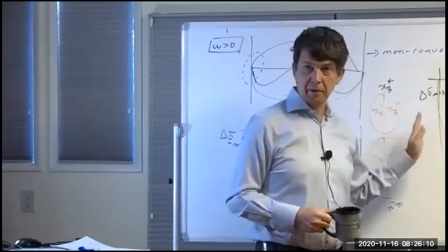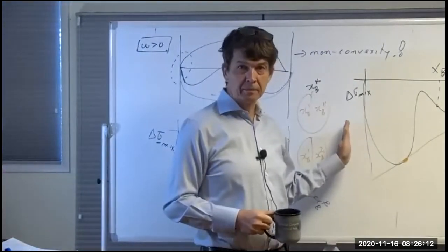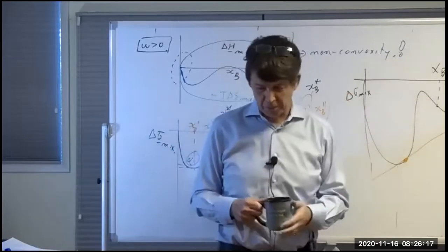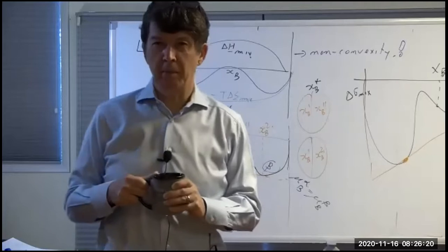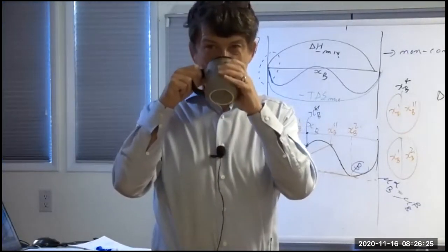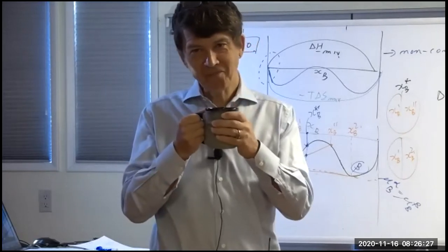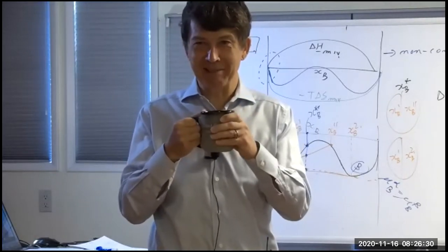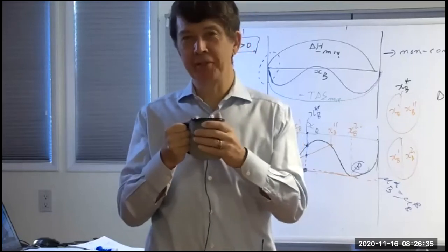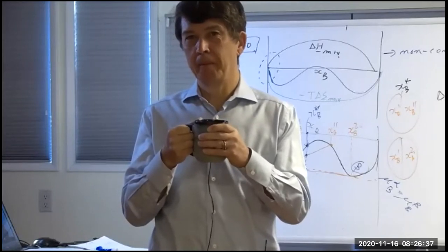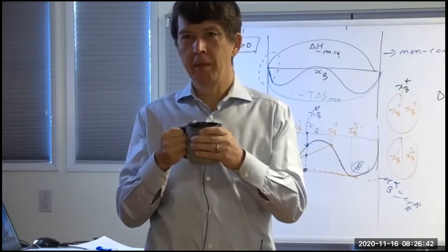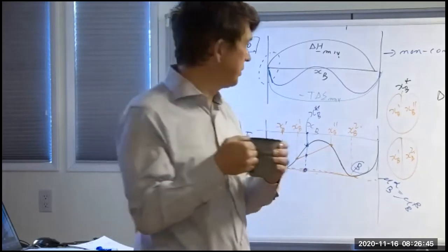If I plot a free energy or a free energy of mixing, kind of same thing, right? They're a different reference state, as a function of composition, what is the meaning of the minimum? That adding material to the phase doesn't change its free energy. That's sort of a mathematical translation, right? But that's how I got there, yeah. But is there a physical meaning to it? It's a trick question, right? So the answer is no. There is no physical meaning to this minimum.